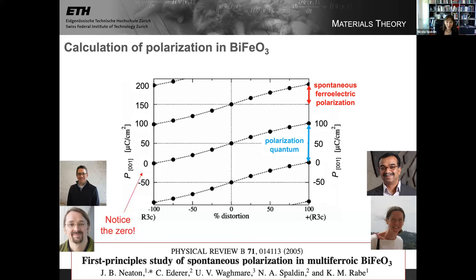Okay, a couple of things I want you to notice. The first is this zero here, and also over here. This is an allowed value for the polarization of the fully ferroelectric structure, if it's in one orientation or another. The allowed values of the polarization are 100, 200, and so on. The spontaneous polarization is 100 minus 50. It's about 50 microcoulombs per square centimeter. But one of the allowed values is zero. And this is not something we noticed at the time, but it's going to be significant for some new results I want to show you later.